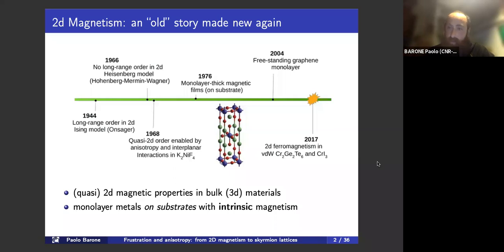But the real revolution, of course, came in 2004, when the freestanding graphene monolayer was realized for the first time. And let me also mention that freestanding graphene was kind of unexpected because of the Peierls and Landau prediction that such really 2-dimensional systems should not exist in reality. And after that, indeed, many other 2-dimensional materials complementary to graphene have been realized, studied and characterized, just to mention the transition metal dichalcogenides that were discussed yesterday.